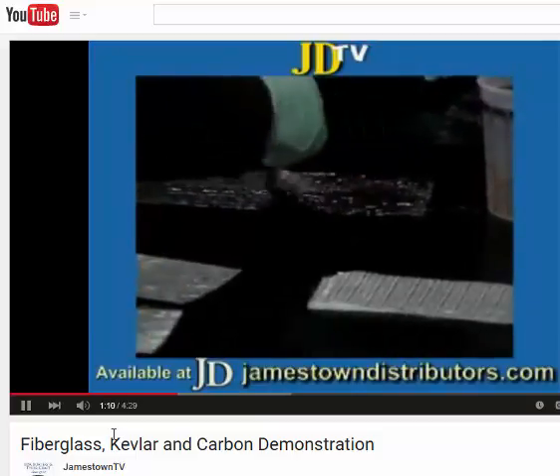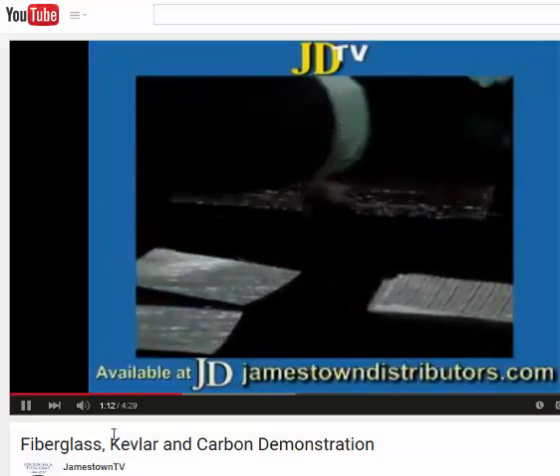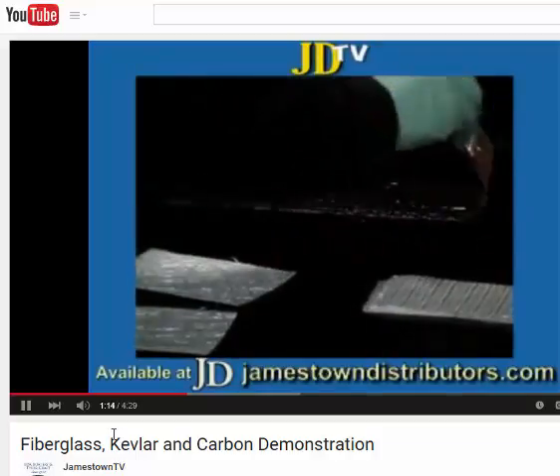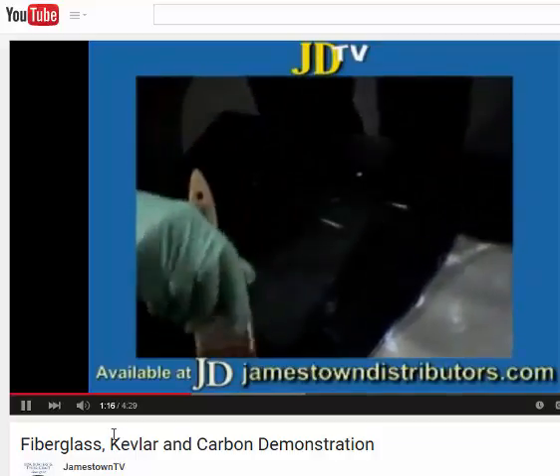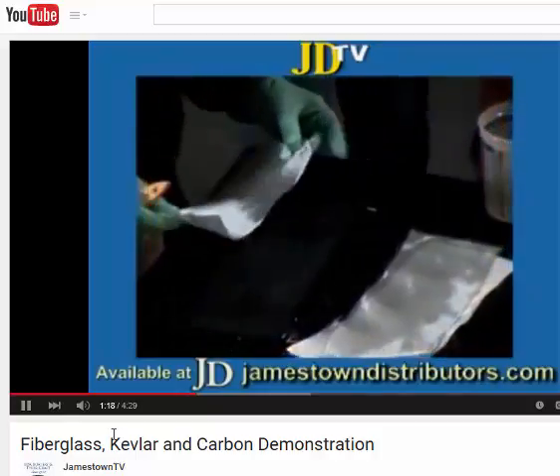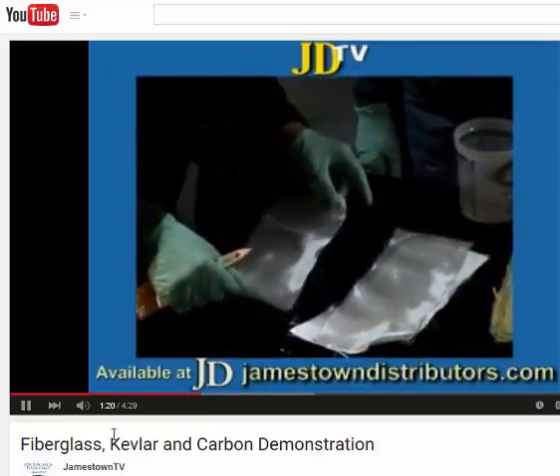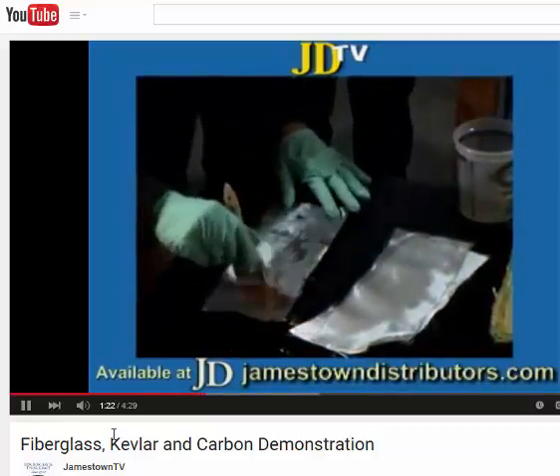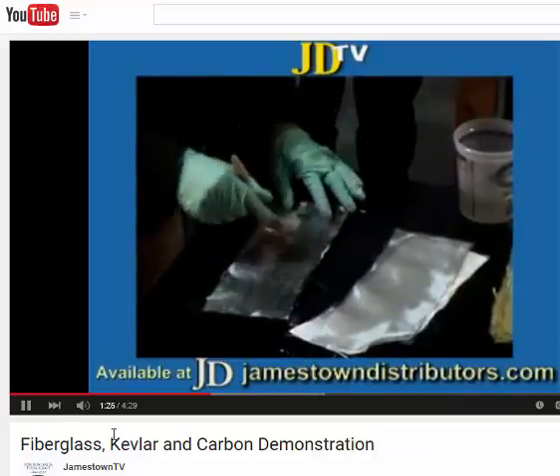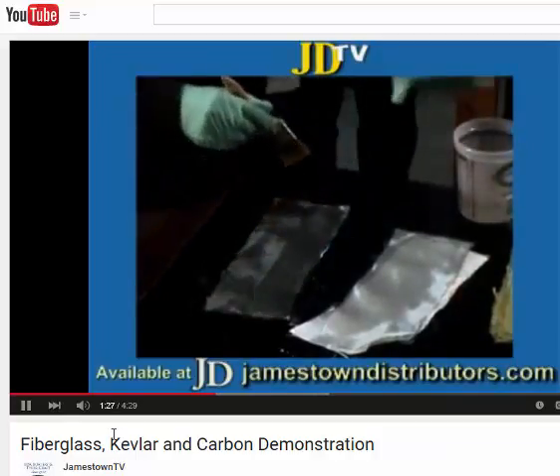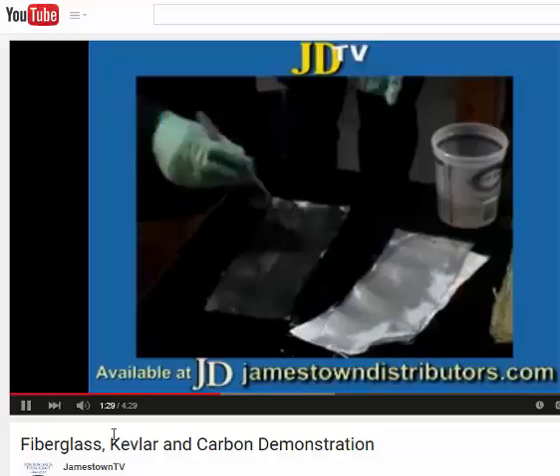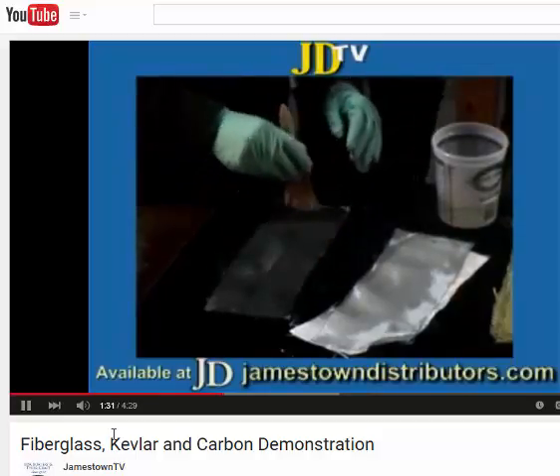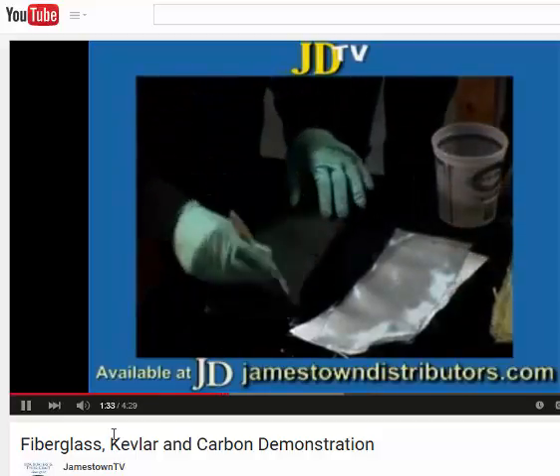Really what you're trying to do with the brush is push the resin into the bundles. So you've got resin coming up and you've got resin going down. So I think the thing to notice here is that the cloth really wets out fast with epoxy. Cloth and epoxy are just made for each other. And you can see that this epoxy is cold, it's thick, which is really not the best situation, but even so, it just wets out beautifully.